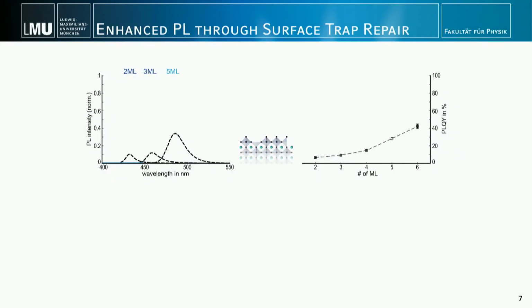Let's next talk about efficiency. To be honest, when we first measured the quantum yield of these samples, it was rather disappointing. The thinnest nanoplatelets, indicated on the right by 2 and 3 monolayers, only had a quantum yield of around 10%. This is not sufficient for reasonable applications. We took a closer look at this, and we thought this might be due to surface defects. This is indicated in the center. So there are some defects, some atoms are missing, and in these errors, you can have recombination without sending out photons.